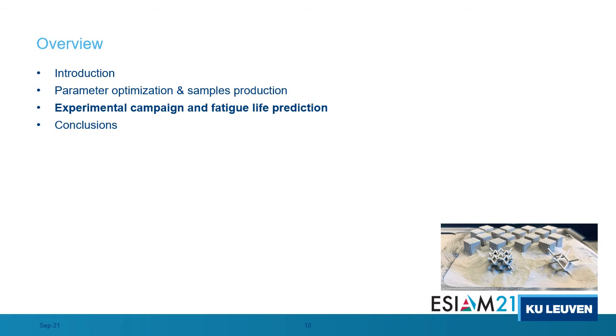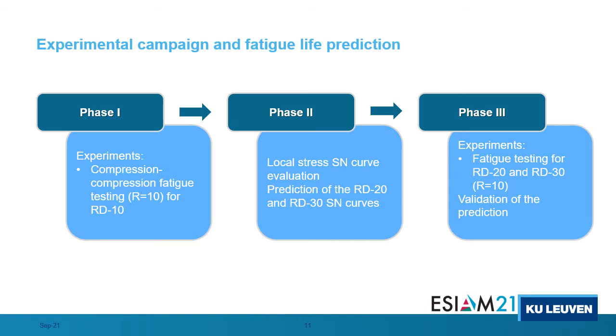Let's now move to the experimental campaign and the fatigue life prediction. The experimental campaign and fatigue life prediction consist of three phases. In the first phase, we carried out experiments on the coupons with a relative density of 10%. The experiments were compression-compression fatigue tests with an R ratio of 10. In the second phase, we extract a local SN curve that we use to predict the fatigue performances of the RD20 and RD30 SN curves. In the third phase, we carried out the same experiments on RD20 and RD30 coupons, trying to validate the predictions that we made in phase 2.